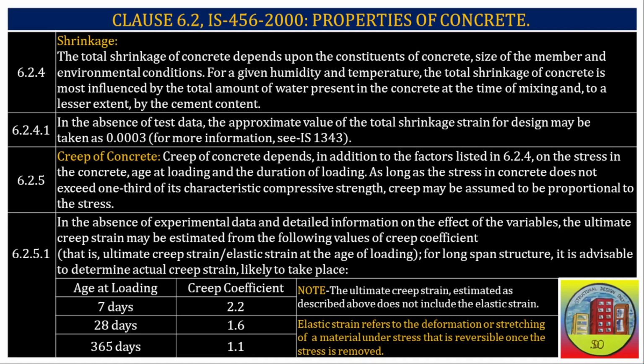Age at loading 7 days, creep coefficient 2.2. Age at loading 28 days, creep coefficient 1.6. Age at loading 365 days, creep coefficient 1.1. Note: the ultimate creep strain, estimated as described above, does not include the elastic strain.